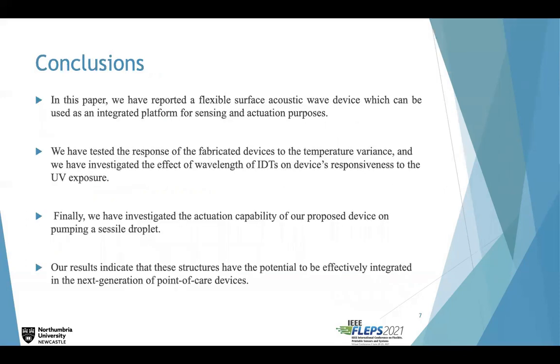As a conclusion, in this paper, we have reported a flexible surface acoustic wave device that can be used as an integrated platform for sensing and actuation purposes. And we have tested the response of the device to the temperature variance and also UV intensities. And we finally investigated the actuation capability of our proposed device by pumping a sessile droplet. Our results indicate that these structures have the potential to be effectively integrated into the next generation of point-of-care devices.